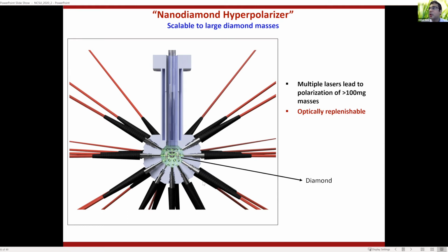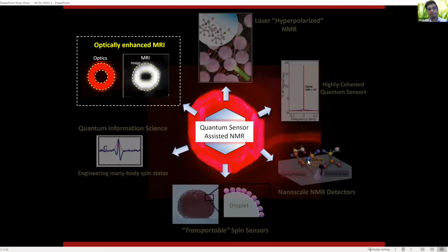But it really shows that this mechanism of polarization per diamond spin is very low power, and the flexibility of optics allows you to do all kinds of crazy things. You can deliver polarization either selectively to a particular particle or to large masses, and it's very easy to design these systems. So these are fiber lasers with a single diamond in the center, diamond nanoparticles in the center. So let me show you some applications of what you can do with this.